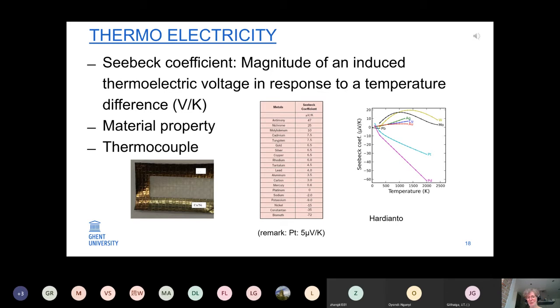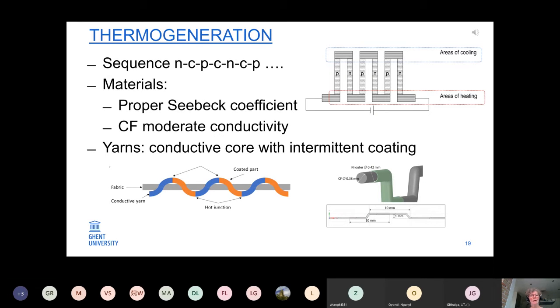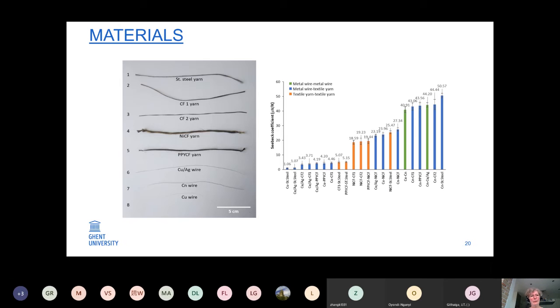So the concept we have chosen is a wire which is coated in dedicated intermittent areas with a second metal. So we have a conductive core coated with a coating at regular places, as you can see here. How it is inserted in the fabric and how it is produced. The materials used, well, these are the materials we have studied. So stainless steel, carbon fiber, nickel, polypyrrole, copper, and silver, and constantan.